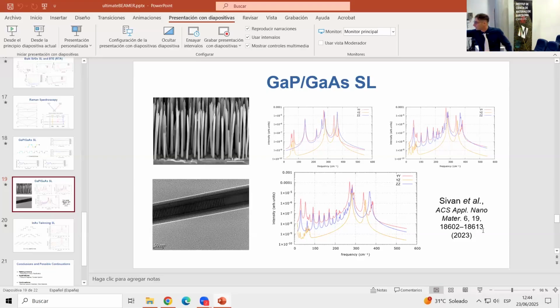I mean, if I look at something like this, I would say, okay, you have enough atoms in the primitive cell. So yeah, you will see a minima in the thermal conductivity. If I look at that, I would say, okay, you have a slight number of atoms inside the primitive cell. You are not going to see a very sharp and pronounced minimum, because you don't have much room for the complete transition from the coherent to the diffusive regime. But still, I think that if you compute that, you would observe a slight minima. Maybe this is the most pronounced correlation you could expect, in my opinion. I see it the same way, I think.